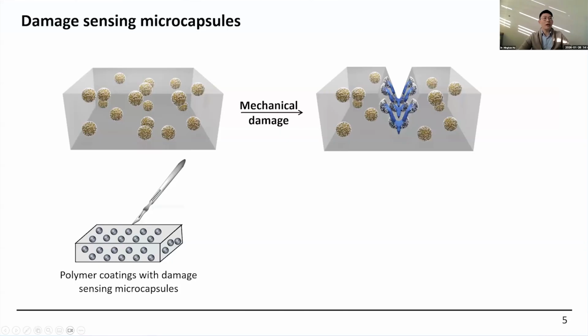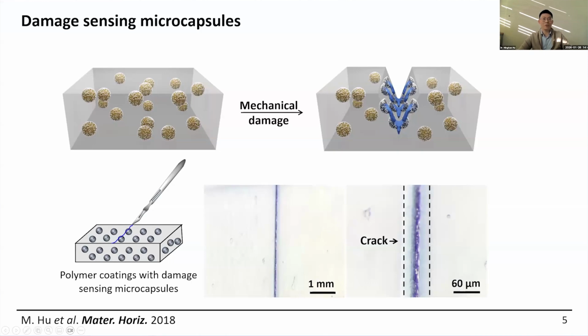This is what we have done previously in 2018. We made these microcapsules, embedded them into polymer coatings, and then cut the coating by introducing damage. We can clearly see that the places with embedded microcapsules significantly show color where the damage is. With this, we can realize damage sensing by embedding these microcapsules.